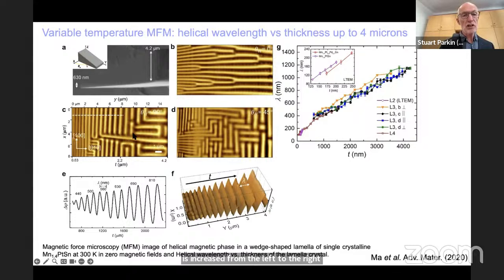And the images C, B, and D are simply obtained by applying a large magnetic field in different directions to the surface of this lamella. And when you reduce the field to 0 or to some finite value, you see these different one-dimensional structures. These are actually all in 0 magnetic field.